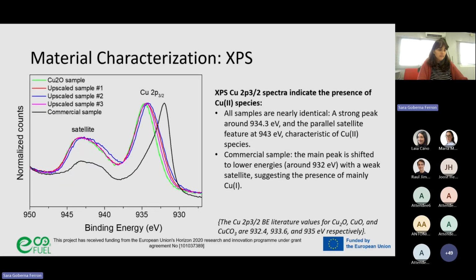Now, regarding the copper signature, all the samples show a peak around 934 electron volts, together with a satellite peak. This is characteristic of the presence of copper-2 species on the surface. The commercial sample, however, shows a main peak that is shifted, and this indicates the presence of mainly copper-1 in the sample.